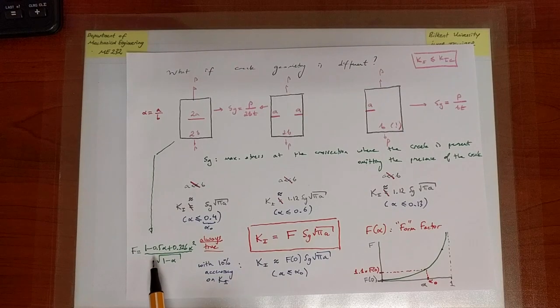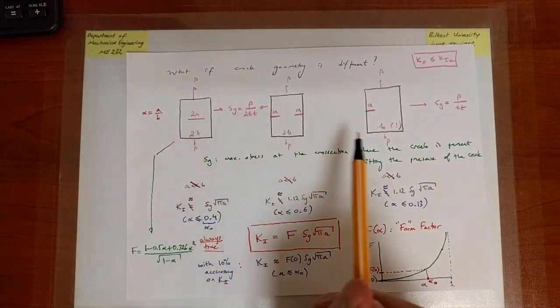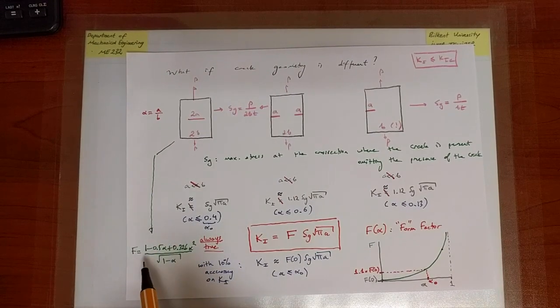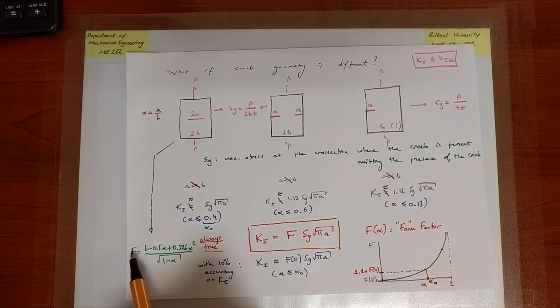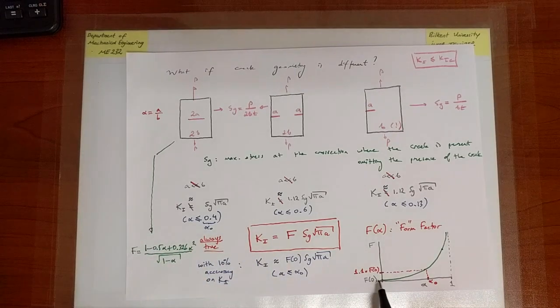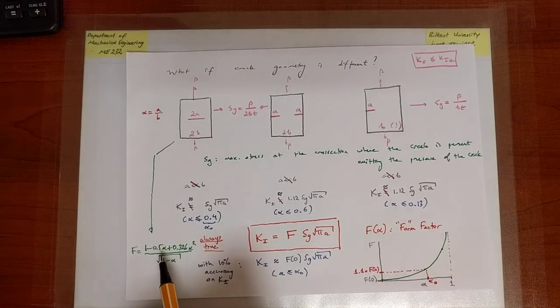Okay? That form of the form factor is special to this case. In general, every case will have its own functional form that we have to make use of. Those are tabulated in your book, so that's where you can have a look at it. Here we can easily check that this curve is meaningful. If alpha is equal to 0, f is equal to 1. It starts from 1, f of 0 is 1 indeed. And if alpha keeps growing to 1, this thing blows up to infinity.